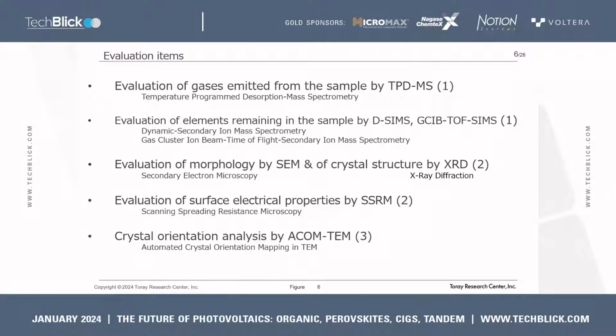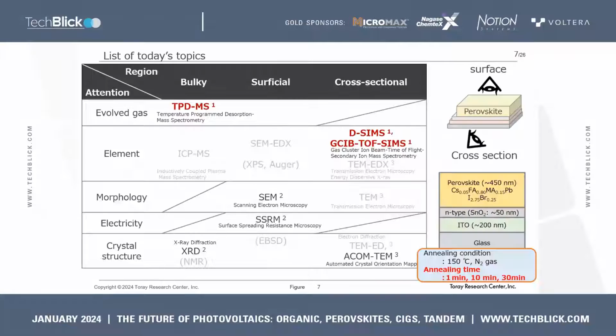Next, we will present a case study of the depth profile of the constituent elements in the film. Third, from the surface, the morphology of the perovskite layer was observed by surface SEM and the crystal structure was analyzed by XRD. Fourth, the spreading resistance of the perovskite layer will be presented. Finally, we will present a case study of the evaluation of the distribution of these crystalline structures.